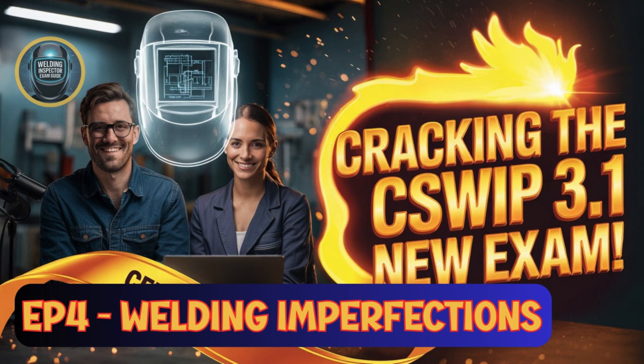Common causes include incomplete slag removal from underlying weld beads in multi-pass welds. You have to clean thoroughly between passes. Or sometimes the slag can flood ahead of the arc if the manipulation isn't quite right and the weld metal flows over it. They can also get trapped in irregularities on the work surface, like undercut from a previous pass.